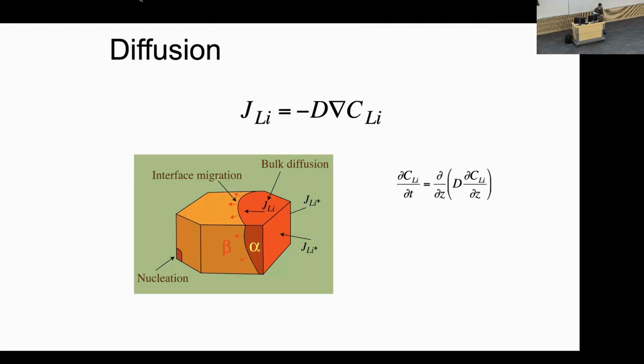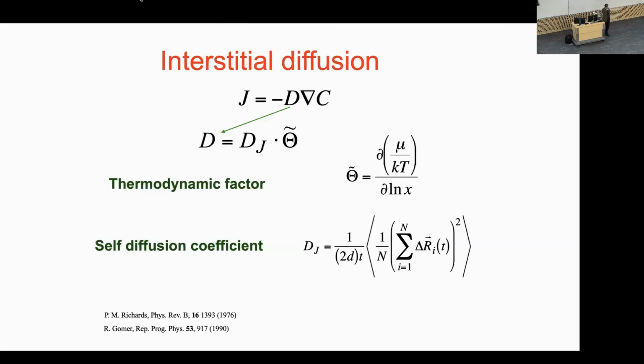So very quickly, and then I'll wrap it up. Diffusion, we can calculate that as well. The nice thing about diffusion coefficients is that you can use Kubo-Green type of expressions, which basically means that you can calculate diffusion coefficients, even though it's a non-equilibrium quantity. You can calculate it by tracking fluctuations that happen at equilibrium, because the fluctuations that happen at equilibrium are a measure of the mobility of atoms. And so there are these complicated expressions like this. The diffusion coefficient you can factor into a kinetic factor and a thermodynamic factor. And so there's a chemical potential in the thermodynamic factor.